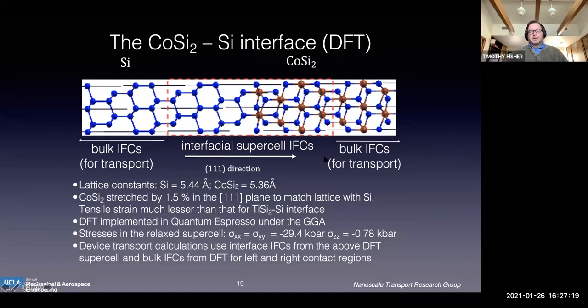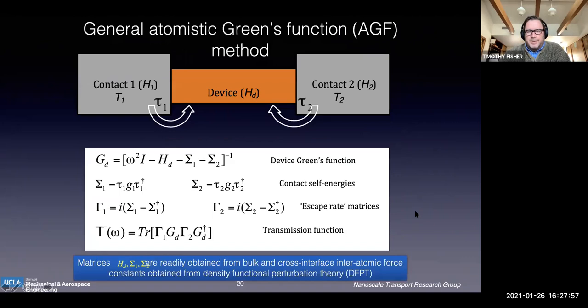And just so everybody knows, and this will come up a little bit later too, whenever you do DFT, it's not like you can take an actual device and say, well, here's a bulk contact of one material and here's a bulk contact of another material and the interface in between. You have to use periodicity. So all the simulations are done in superlattices. But we just make the superlattices big enough so that we can focus on one interface without the influence of nearby interfaces. And we tried to normalize that out or make sure that our superlattice size was such that we could make the argument that it was not a big effect.